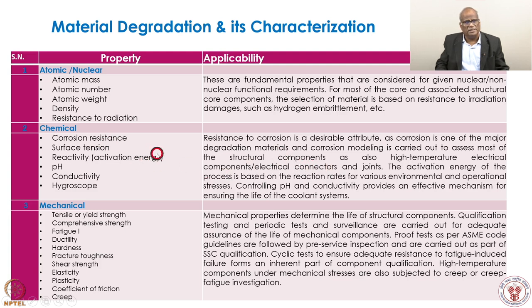Second thing is how we maintain in operation. In operation, pH and conductivity are the parameters that we see, so water chemistry measurement itself will reduce the corrosion degradation. So material, and then monitoring of process parameters. Then mechanical system. Mechanical system has a host of things, for example, creep. Creep comes into action when there is high temperature, under which the material properties change, and under stressful conditions. So creep: high temperature and a given stressful condition result in the creep phenomenon.